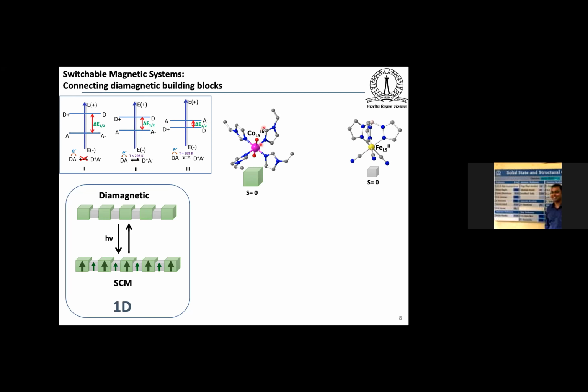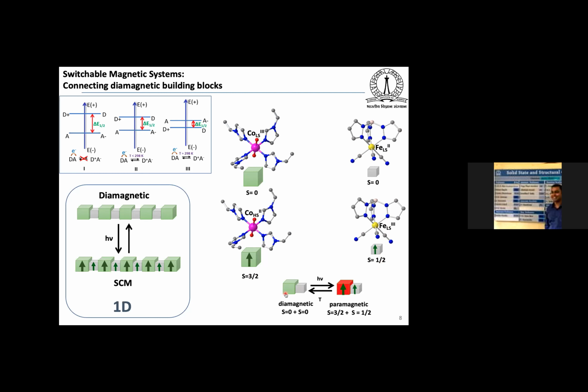So we have chosen this cobalt 3 low spin system, that is S equal to 0, and iron 2, this is the tris-pyrazolylborate cyanide building block that was synthesized by my supervisor Rodriguez in 2002. But another interesting thing is that you can go to cobalt 2 high spin state, where you can have S equal to 3/2, and that iron 2 also can become iron 3, and then you can generate spin S equal to 1/2. And when the system is diamagnetic, if you increase the temperature, you will go to the paramagnetic state. Also, you can irradiate the system at low temperature, and you can also get from diamagnetic to paramagnetic under irradiation at one particular temperature as well.